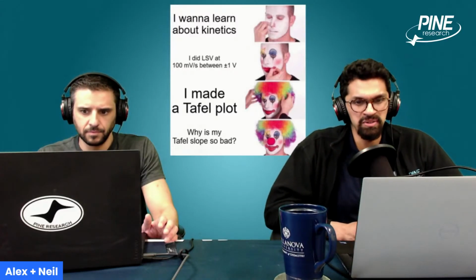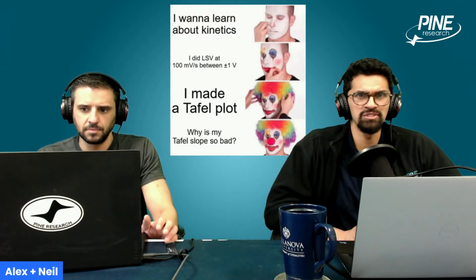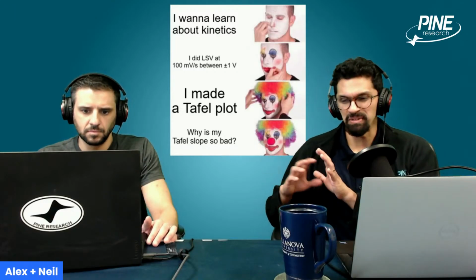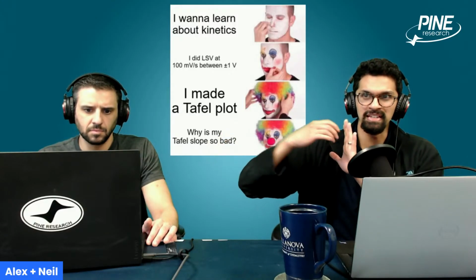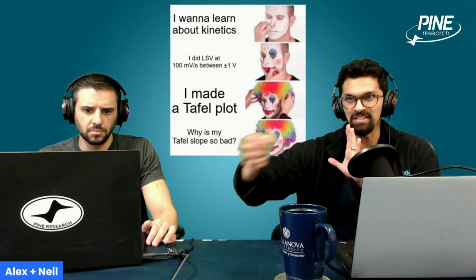this actually reminds me of the Frumkin effect as well. When you're at very, very low concentrations of electrolyte, you can get really weird behaviors because of migration effects. Because you now have an electric field that extends into the solution, it pulls ions. You get almost a doubling effect. The molecule moves because it feels the migration from the electric field of the electrode, but then it gets instantly countered by the migration of solvent or electrolyte that repels it, and then you get a new movement. There's a whole Frumkin effect that I need to learn more about.